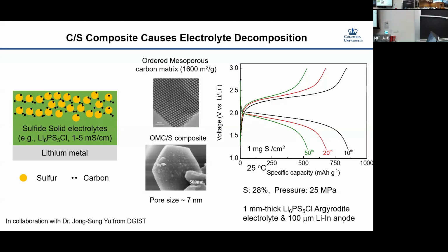When people study liquid lithium sulfur batteries, they often use the mesoporous carbon matrix, which helps to increase the electron conduction in the cathode. And we collaborated with Dr. Jong-Sung Yu from DGIST, Korea. He developed a very good mesoporous carbon matrix, which has shown to be very good in liquid lithium sulfur batteries. And we combined it with the sulfide solid electrolyte.